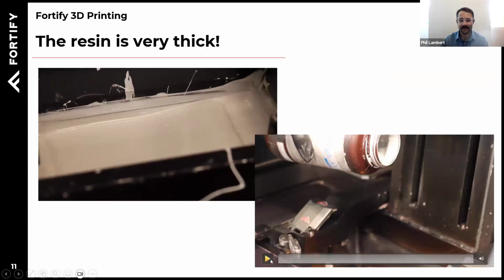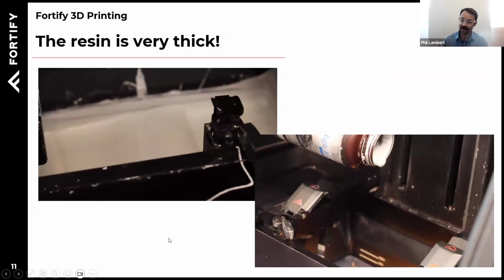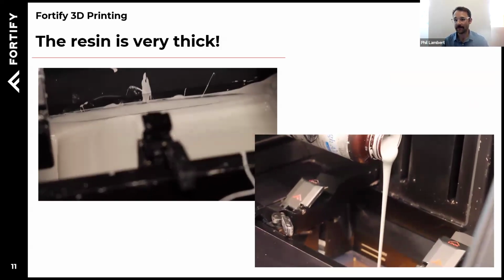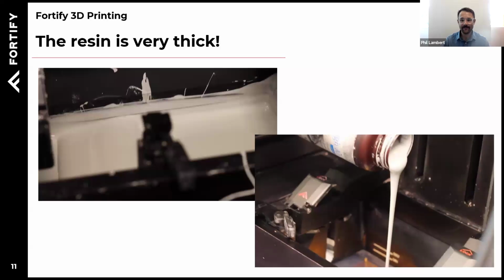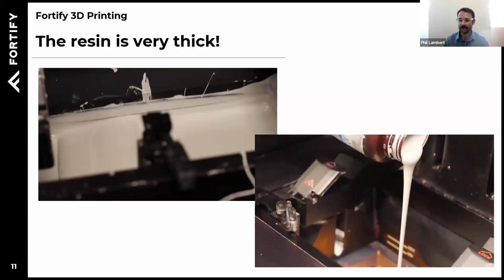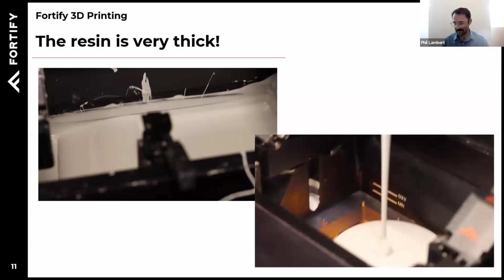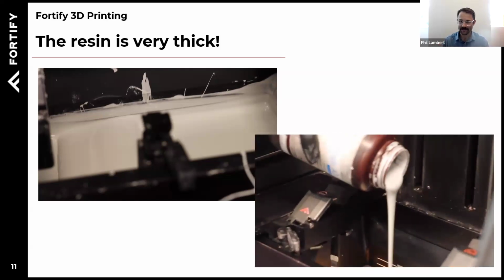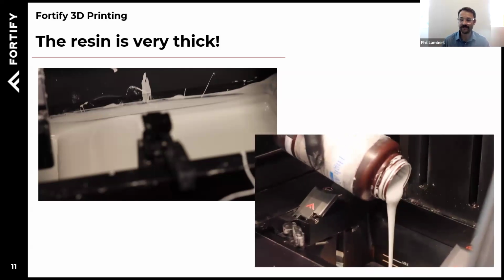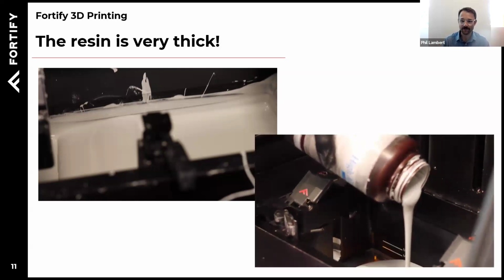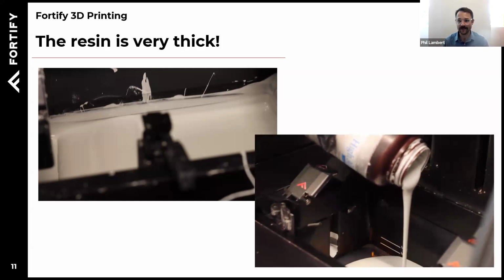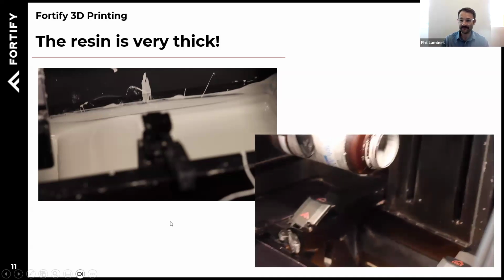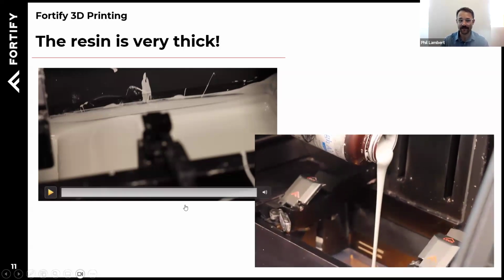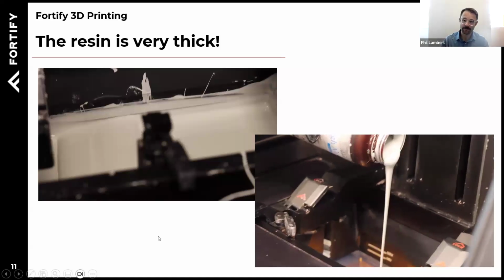So just to give you a point of reference of how thick some of these materials can be: when you add fibers, fibers tend to introduce the final part behavior that you're interested in having. The more fibers you add, you tend to impact the viscosity in a pretty dramatic way. And viscosity is sometimes manifested here in this image as thick material. I should say it always is. Rheology also plays a role here, where these materials can introduce non-Newtonian behaviors depending on the particle package, depending on the size and morphology of those particles, the content. Anyways, the point here is that these fiber-filled resins tend to get quite thick, and we need to have technology to process them, and that's where Fortify has innovated.